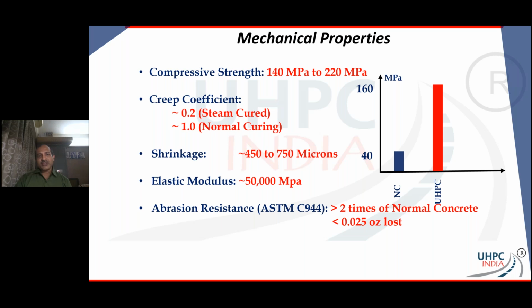The second point I would like to raise is that the creep coefficient of UHPC is extremely low. Even with normal curing, normal concrete exhibits a creep coefficient of about 2, so you do a 2 plus 1 in your creep calculations or deflection calculations. But when it comes to UHPC, the creep coefficient, even for normal curing, is close to 1.